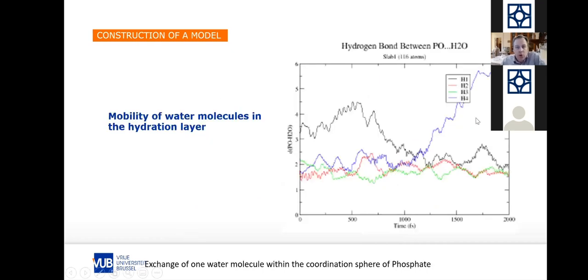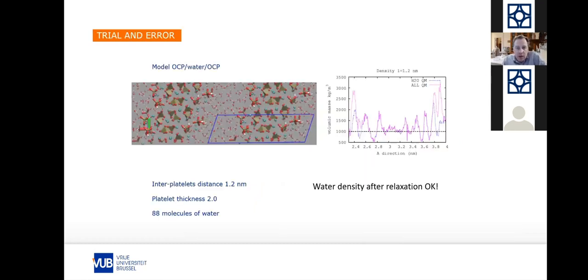Let's see. Good. Okay. So we see here the mobility of water. We saw an interaction and an exchange of water molecules from the bulk water to the hydration layer, and vice versa. We can also add some extra water molecules in order to see what is the effect on the density of the water in between, because we are working in a confined environment. The 1 nanometer or 1.2 nanometer that you see here is very small. So we can probably think of some special properties that are emerging out of this model.